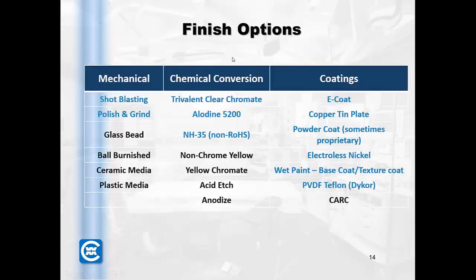If we look at some of the different finish types, there are 3 categories that we break down into this table. Mechanical finishes, and that meaning shot blasting or glass bead blasting, any type of part-on-part or a media that's blasting against a part. That's what we mean by mechanical. Conversion coatings are typically platings that the parts will go through. These are typical pre-treatments in a lot of cases that are used before the final coating will be applied. But sometimes these chemical conversions are used on their own. So if the part is not a cosmetic part and you just want a plating or type of finish to add some corrosion protection, then a straight chemical conversion process will be fine, and just leave it like that.